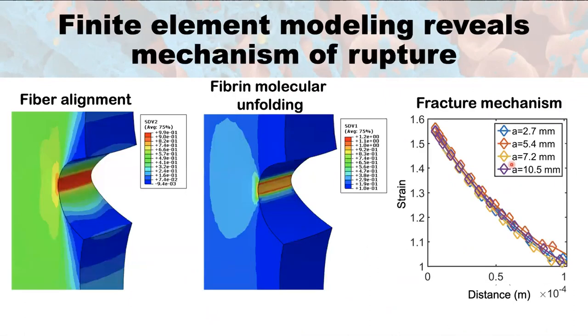So if we look at the results from the finite element modeling, we see that just like in our experimental results, there is fiber alignment right ahead of the region of the crack tip that is seen in red here as being the most aligned portion of the sample. Now, the model is able to take it a little bit further than we were experimentally and get a little bit deeper into some of the mechanisms.